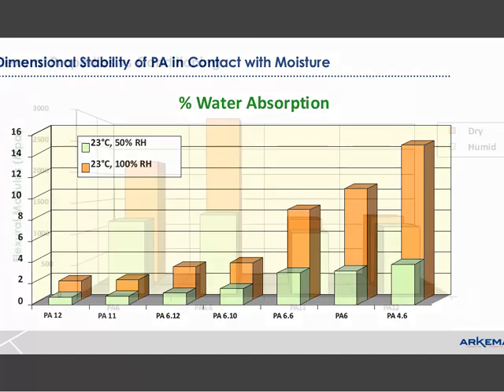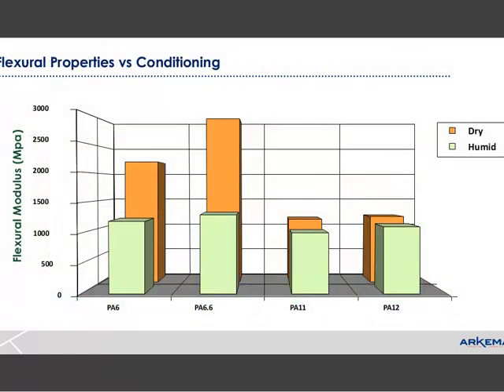But another way of showing this would be looking at the flexural properties. And this is comparing long-chain polyamides on the right to shorter chain on the left. And what you see here is that going from a dry to a humid condition, the long-chain polyamides don't change that much in flexural properties, whereas the shorter chain, because of water absorption, will have significant property changes relative to moisture absorption.